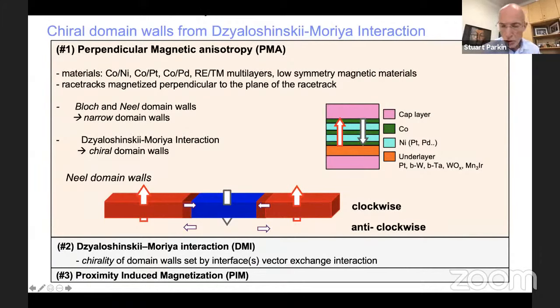So the cartoon shows a racetrack with blue and red domains pointing up and down. And in the middle, when the moment rotates from up to down in the domain wall that is shown, in the middle of the domain wall, the domains will either be clockwise oriented if, for example, the cobalt layer is grown on platinum, or anti-clockwise oriented if the cobalt layers are grown on tungsten. And this is shown in these cartoons.